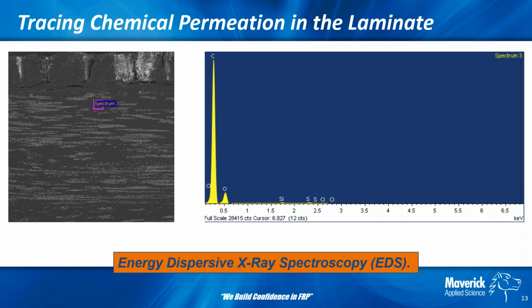So at this point, our veil layer is approximately 10 mils. We're about another 10 mils down. And generally what we found was between 20 and 30 mils deep into the corrosion barrier is where, to the extent that it permeated into the laminate. To give you a perspective, our typical corrosion barrier is 100 mils thick and we're 30 mils into it, say. So really we're only a third into it after almost 20 years. So really not too bad for sulfuric acid service, particularly at a fairly hot temperature.